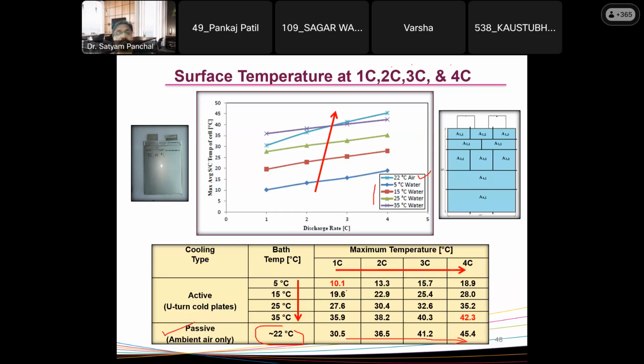But if you look at the 5 degree, at 1C, max temperature is 10 degree, and at 4C, max temperature is 18 degree. If you increase the boundary condition, at 4C, the temperature is 42.3 degree C. So it is basically concluded that increase in C rate increases the surface temperature distribution and the heat generation from the battery, and increase in the boundary condition increases the surface temperature.